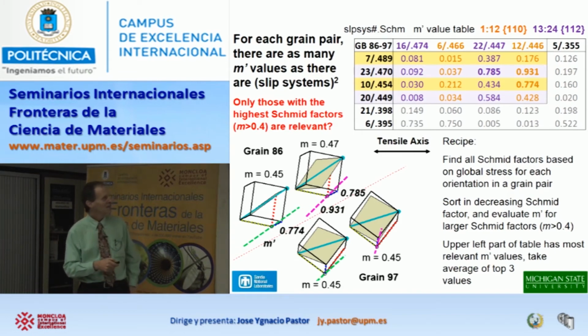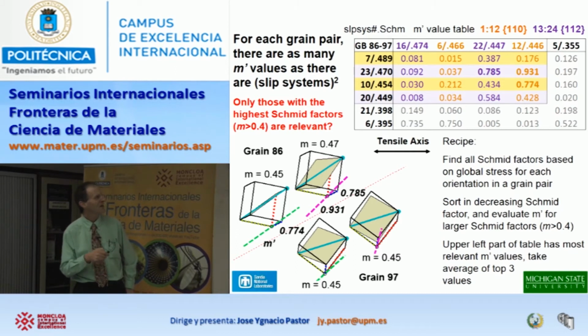So what I'm doing here is sorting through the 24 slip systems in a BCC material that we can look at on 110 planes and on 112 planes. I'm sorting them from the highest Schmid factor, 0.47, 0.466, going downward in grain number 97, which is this one. And then in grain number 86 right here, I'm doing the same thing. There's the highest Schmid factor, second highest, third highest. And they're gold or purple according to whether they're 110 planes or 112 planes.